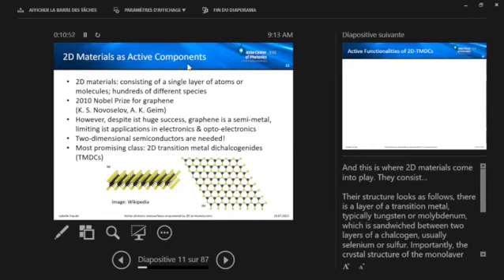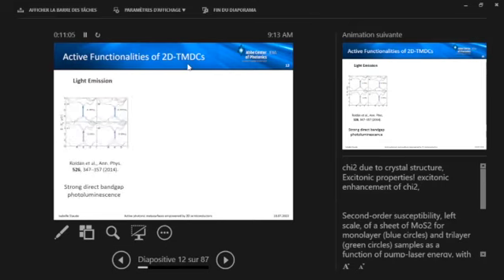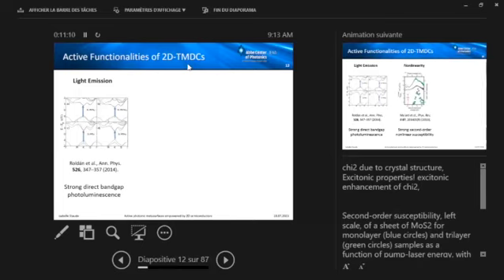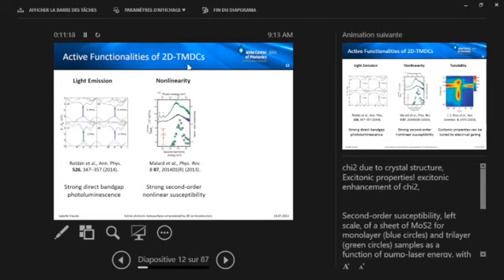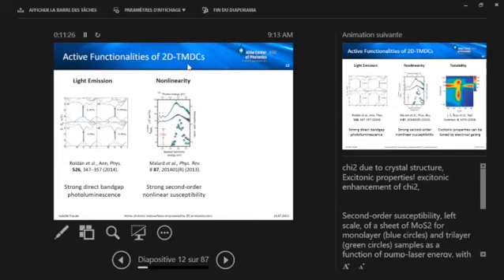And what I should mention is what's quite important is that the crystal structure of these materials lacks inversion symmetry, and I will come back to this point several times. Okay, so what active functionalities can these 2D TMDCs provide us with? And so the important thing is, if we thin them down to the monolayer phase, they basically become direct bandgap semiconductors, so they provide us with a strong photoluminescence. That's already nice. Then, because of the lack of inversion symmetry of their crystal structure, they have a non-vanishing second order nonlinear susceptibility.